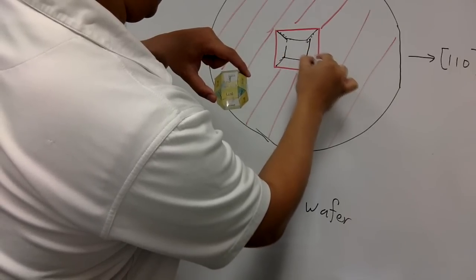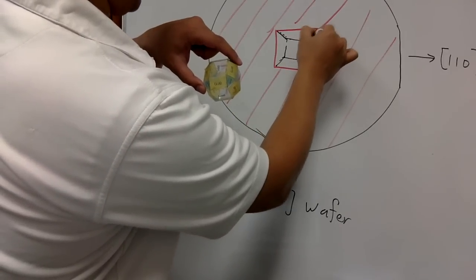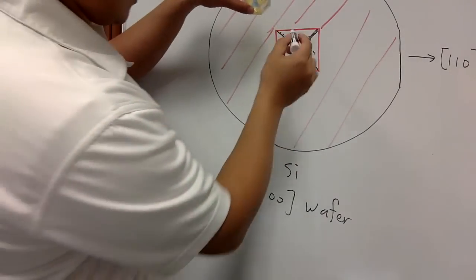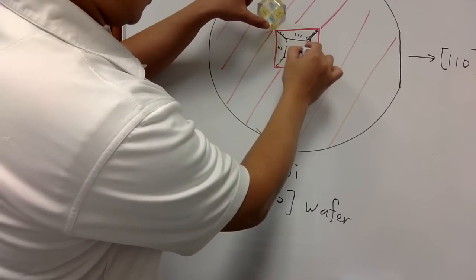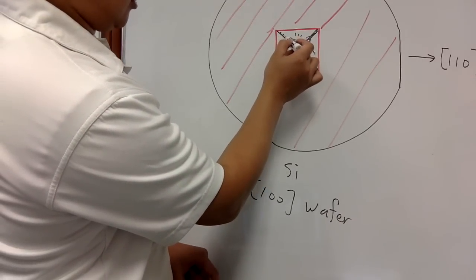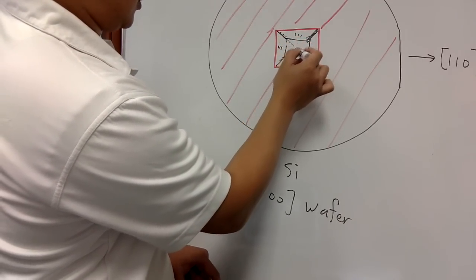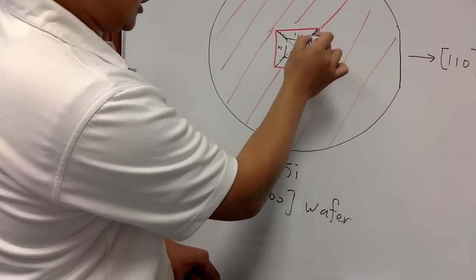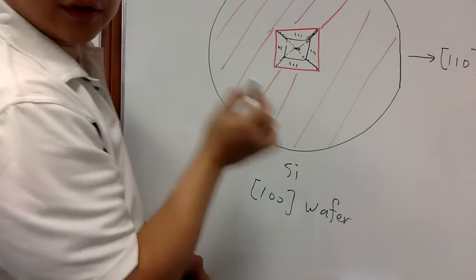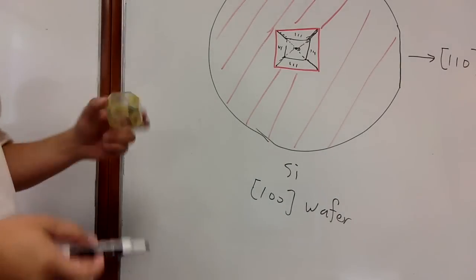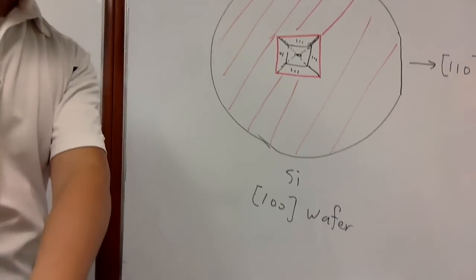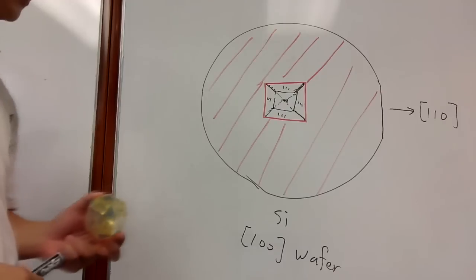These are the four [111] planes — and in the middle you are still looking at the (100) surface. If you keep the wafer in the solution, this will continue to proceed, and because this is a rectangular structure, it will eventually form a pyramid shape. This is the simplest case and it's also the case in the homework.